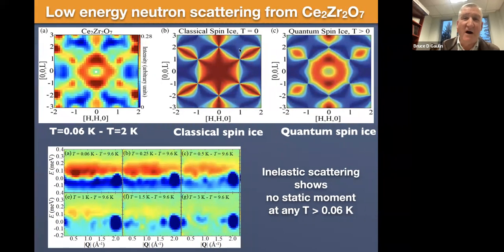Okay, so I showed you the high energy physics as determined from neutron scattering. Now I'm going to show you the low energy physics. And it's best to start down here at the bottom, where I show you energy versus mod Q. This is both powder neutron scattering data and single crystal neutron scattering data which has been angularly averaged. Actually, I think this is all powder data. And you can see that this is a temperature difference data set: some low temperature minus 10 Kelvin. And 10 Kelvin is much higher than the Curie-Weiss temperature in the system. So at 10 Kelvin, whatever this is, it's behaving like a paramagnet, and you're subtracting that off.